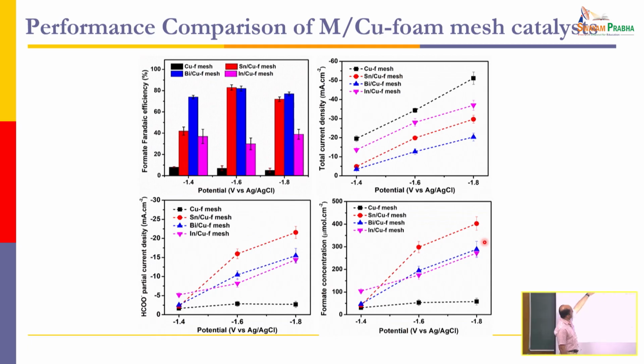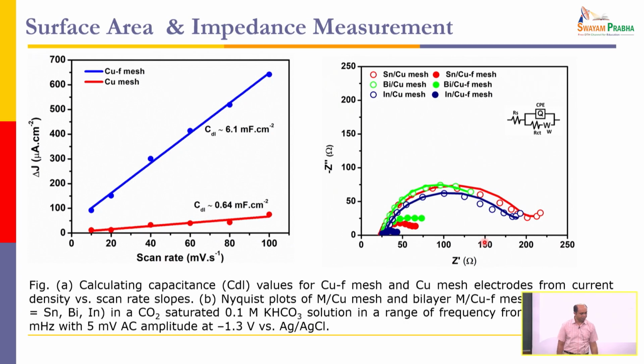Here you can see, the higher the value, the higher the Faradaic efficiency. We are looking at formic acid as a product. More formic acid is formed in this condition at 1.6 volt, where close to 80% Faradaic efficiency is there, and both catalysts are good in this case. Like that, we have done this for different catalysts and characterized them to find out which is the best catalyst that we can use for formic acid production.